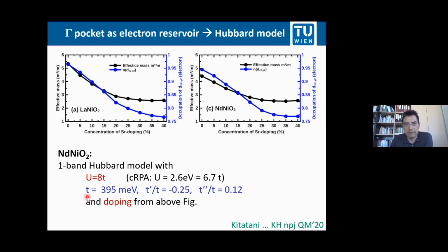We can calculate by a Wannier function projection our hopping elements. We can calculate the U for the single band with cRPA. From tons of experience with other materials, we know if you take a static U instead of a dynamic U, which we would have in GW plus DMFT, as advocated, for example, by Antoine, we have to increase this U by about 0.5 eV. That's just experience from tons and tons of transition metal oxides. So instead of the 7t for the U, we get an 8t for the U for this neodymium nickel oxide, NdNiO2.